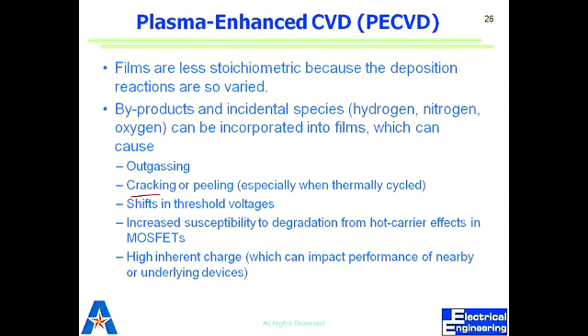There can be issues with contamination in case of PECVD, which can result from the products that come out, hydrogen, nitrogen, getting incorporated back into the film. They can ultimately result in film degrading due to outgassing, cracking, changes in threshold voltages of the devices. Hot carrier effects. Hot carrier effects is when charge carriers push through an insulator, basically degrading MOSFETs and having much more inherent charge. So if you get those species which are contamination, they can have electrical as well as mechanical issues with the devices.